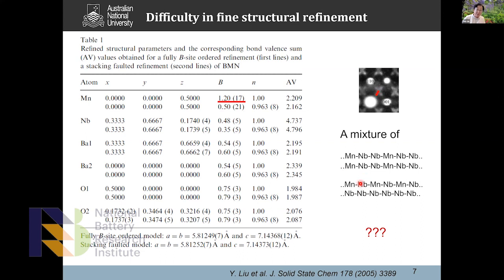In the real case, these are two extremes, a 1-to-2 and a 1-to-1 ordering, but in the middle you don't know the correlation length; the stacking faults can happen in the material with different correlation lengths. That's why you get this diffuse scattering. They all combine together to give you an image like the diffuse scattering as a cross section.